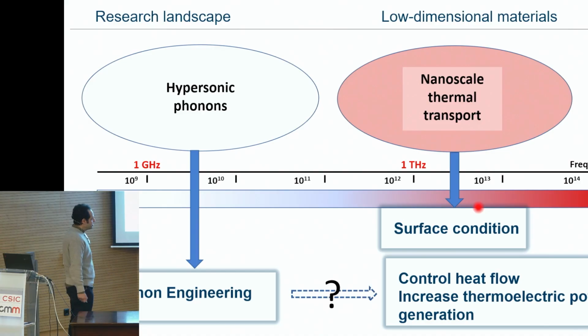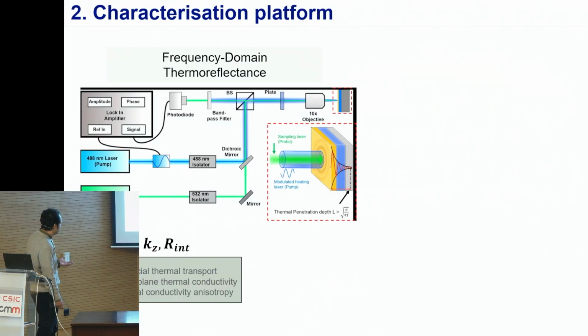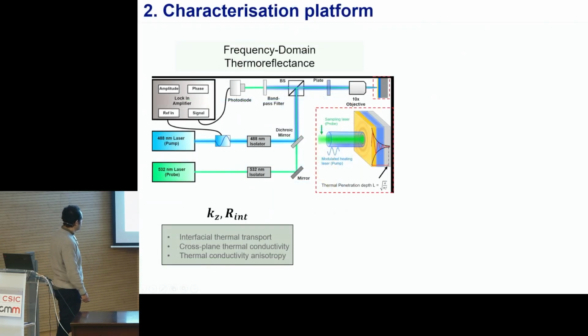And in order to do this, we need to work with advanced thermal characterization techniques, and this is what we are developing in my lab. So first we are working with the frequency domain thermoreflectance, an interesting technique where you can probe interfacial thermal transport, you can measure the cross-plane thermal conductivity, and you can determine the thermal conductivity anisotropy, which is interesting, in many cases, depending on the film thickness that you have. I will speak later on about this technique.